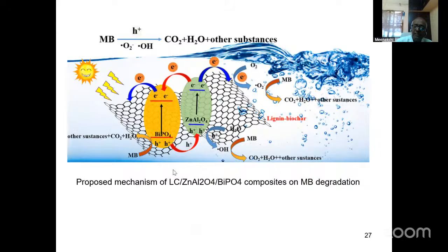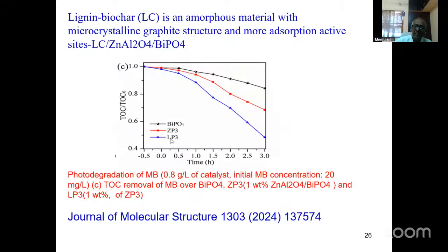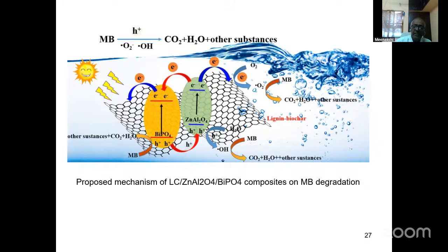So this is showing the mechanism. This is bismuth phosphate, and here you can see bismuth phosphate and zinc aluminate. Actually, the electron is excited from bismuth phosphate or zinc aluminate, and the electron is captured by the lignin biochar, and this is given to oxygen forming superoxide radicals. When the electron is captured, automatically the hole is freely available. So this electron-hole separation is very effective because of the abstraction of electron by the biochar. This is the mechanism proposed for degradation of methylene blue by lignin biochar zinc aluminate bismuth phosphate nanocomposite.